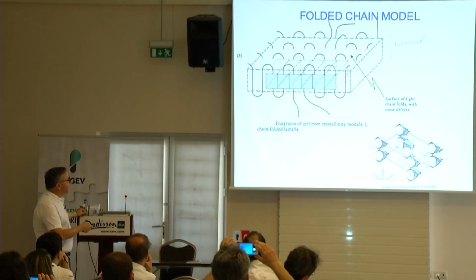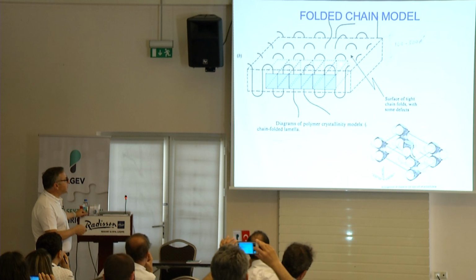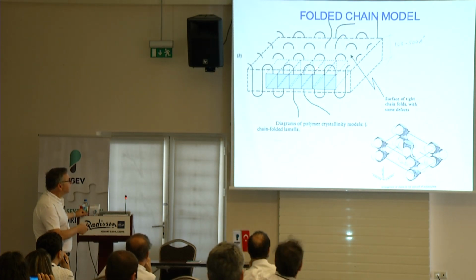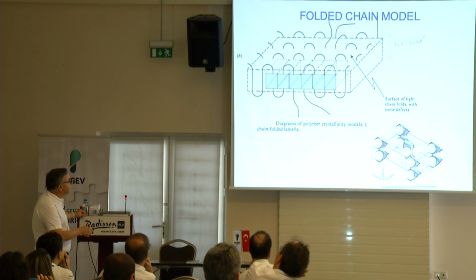And this is the other model. They call it the chain folding model. Basically, this is called a lamella, okay? And the crystal structure is part of the lamella. They just simply stack up. So a chain arrives and simply folds back and forth, back and forth, back and forth. Once in a while it comes out, and so on. And these lamella sizes are on the order of 100 to 500 angstroms for most of the materials.